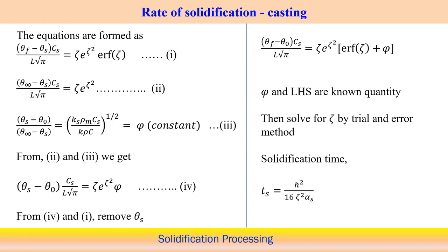I am not going into details of how we reach this, but we can reach this equation along with the boundary condition: theta f minus theta s, C s by L root pi, equal to the error function of zeta. We have already discussed the definition of zeta, so I am not repeating it here. Then the second equation: theta infinity minus theta s by L root pi C s into zeta e to the power zeta square. And the third equation: theta s minus theta 0 divided by theta infinity minus theta s equals k s rho m C s by k rho c.